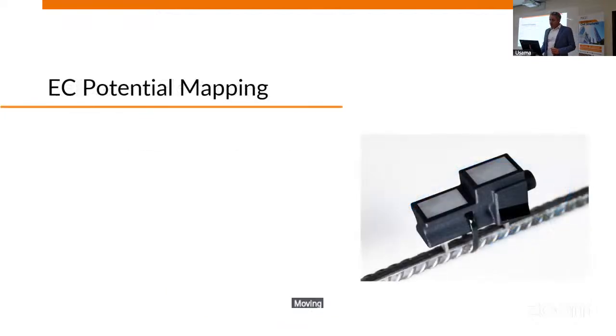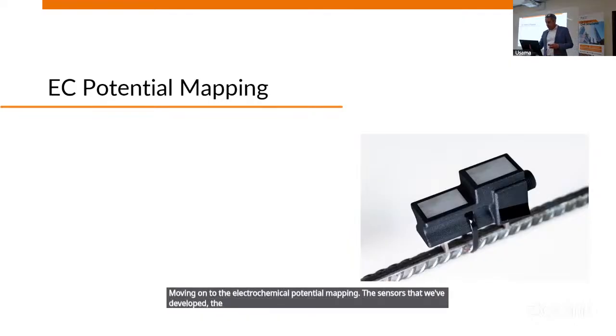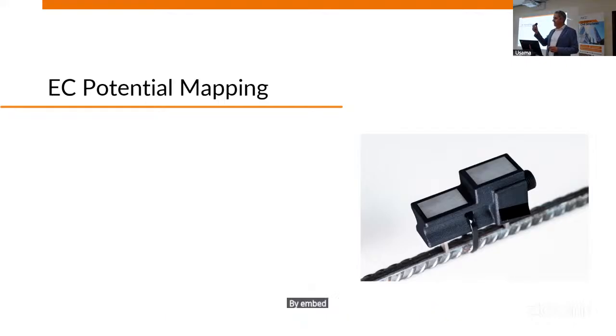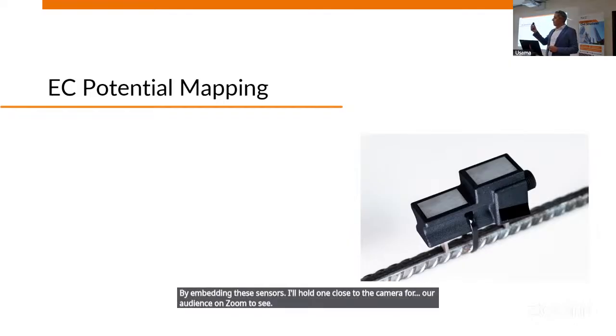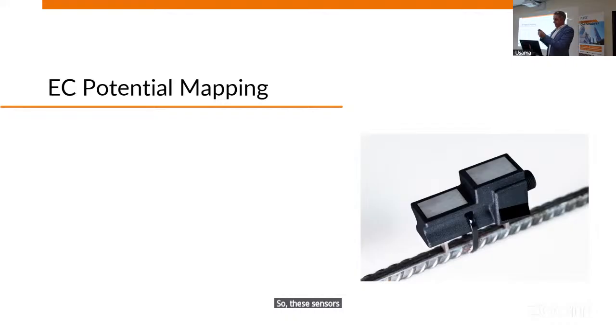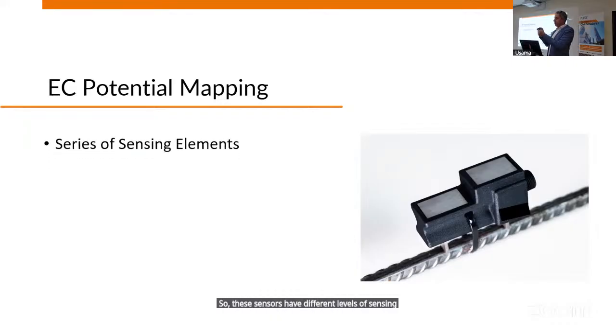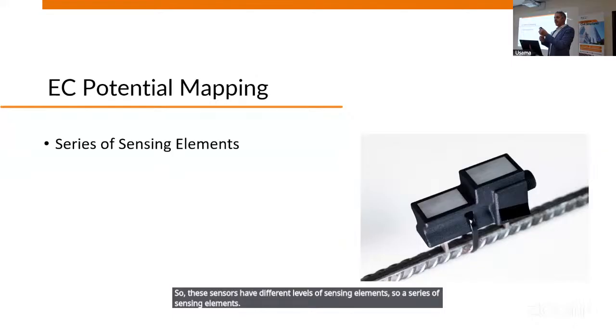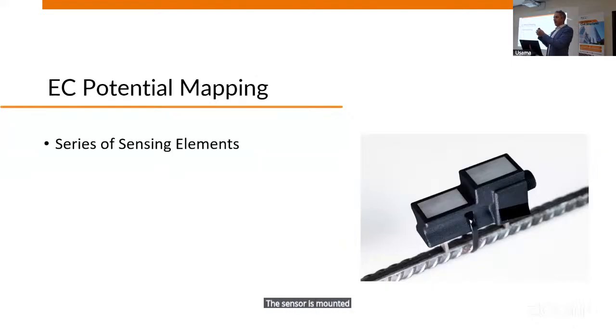Moving on to the electrochemical potential mapping. The sensors that we developed, the electrochemical potential mapping, really maps out electrochemical potential by embedding these sensors. I'll hold one close to the camera for our audience on Zoom to see. So these sensors have different levels of sensing elements. So a series of sensing elements. The sensor is mounted on rebar, on the first layer of rebar. So it is tied to the first layer of rebar. It sits within the concrete cover.